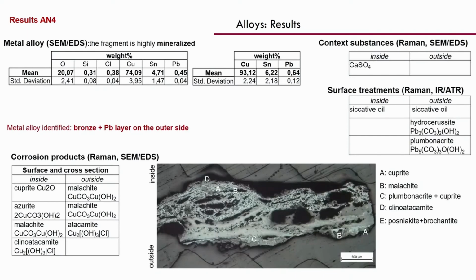Here, another example of bronze. Even in this case, the fragment is highly or totally mineralized. And you can see even here the presence of tin, but we have a presence even of lead in this case. So we could think of a ternary alloy. But as organic protective, we found here a siccative oil, so an oil was used with the aim to protect the surface.